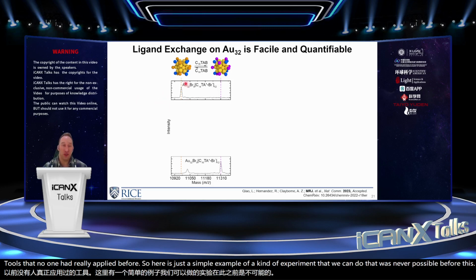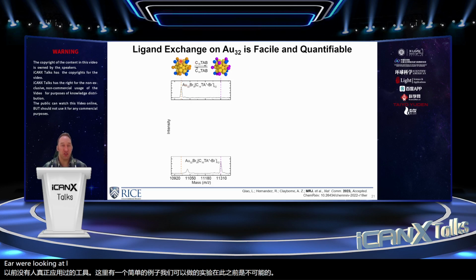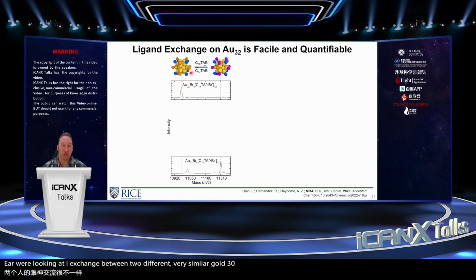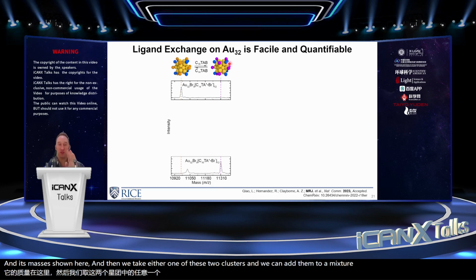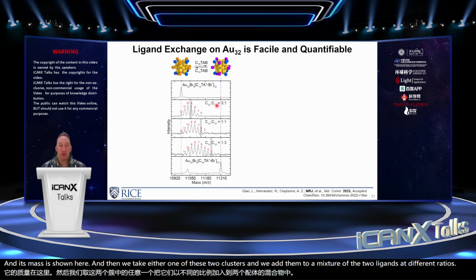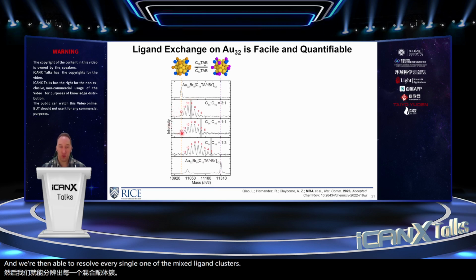before this. Here we're looking at ligand exchange between 2 different, very similar gold-32 clusters. So on the left here, this is a gold-32 cluster where all of the ligands have a 14-carbon alkyl chain. It has a mass shown here. This is a cluster where all of the ligands have a 16-carbon alkyl chain, and its mass is shown here. And then we take either one of these 2 clusters, and we add them to a mixture of the 2 ligands at different ratios. And we're then able to resolve every single one of the mixed ligand clusters. So 12 here, let's say 10 here represents 10 C14 ligands and 2 C16 ligands because there are 12 total